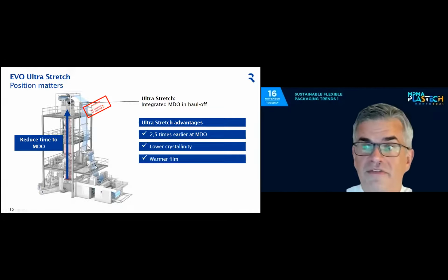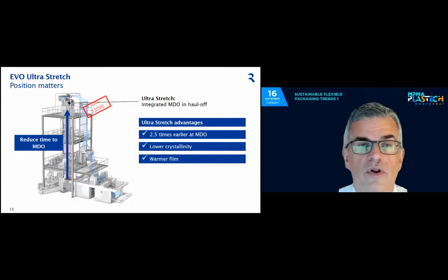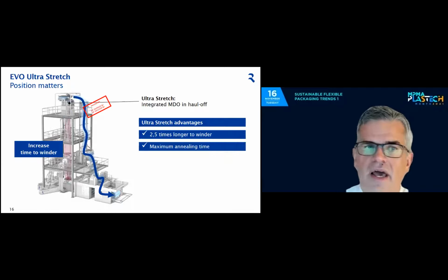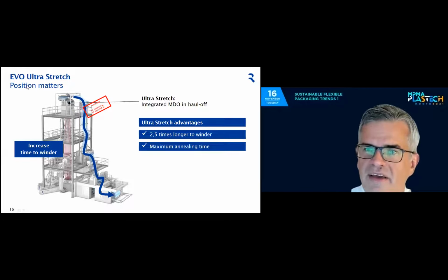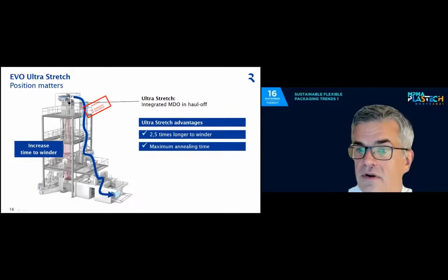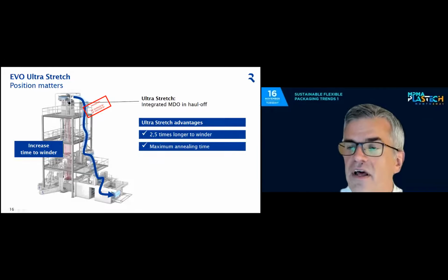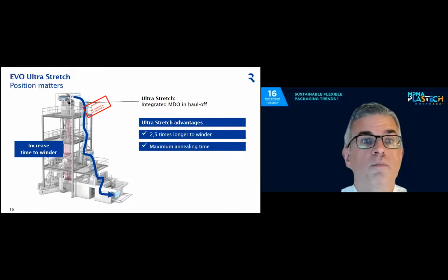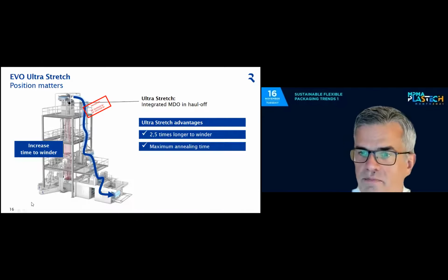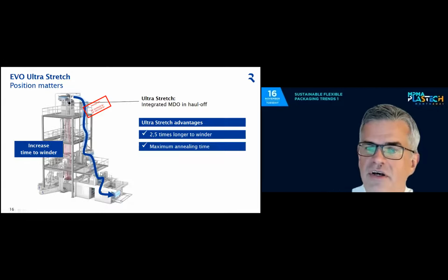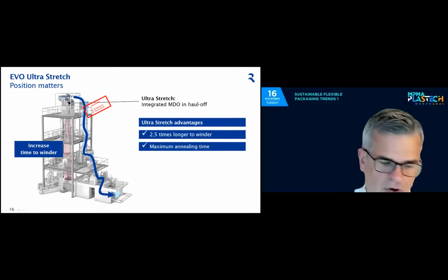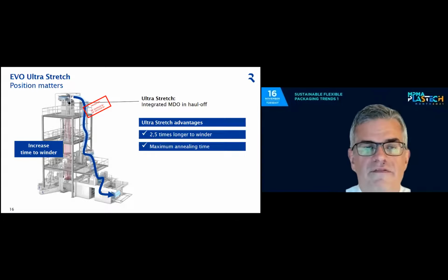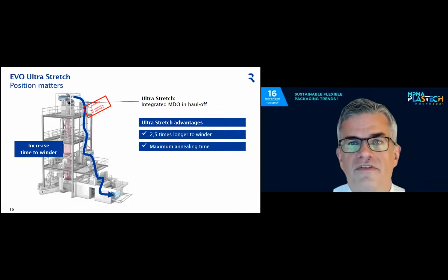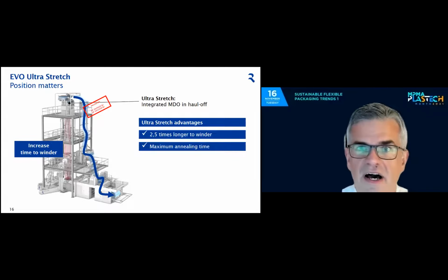So the film has lower crystallinity, and you need less energy to heat it up to stretch the film, and vice versa, the film has all the way down to the winder to anneal, to shrink. Again, 2.5 times longer than if you put the MDO on the level of the first stage, just above the winder. So, final conclusion, if we talk about stretching, it's very easy.